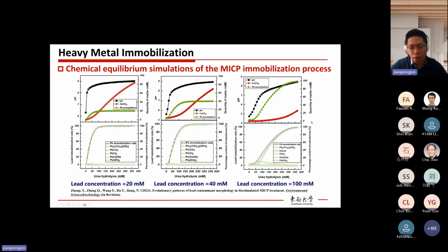And if we have even more lead in the system, then the precipitation is dominated by the lead, and we only have a little bit of calcium carbonate in the system. And the second row shows different lead precipitation species. And due to time limitation, I will not introduce them in detail.